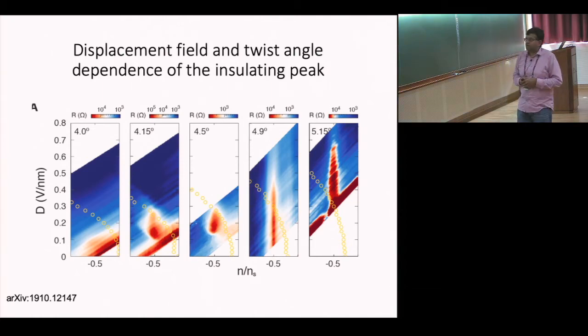So it's a picture of, if you wish, moderate correlations, where the state on the one hand is fixed exactly at half filling, so it's like a Mott insulator. But on the other hand, it does care about the density of states of the system. And when the density of states at half filling becomes sufficiently small, then you have a metal to insulator transition.